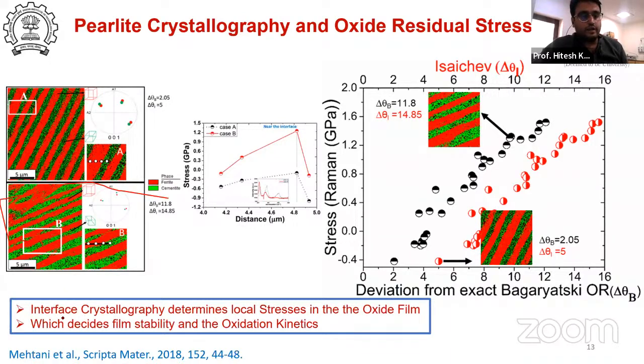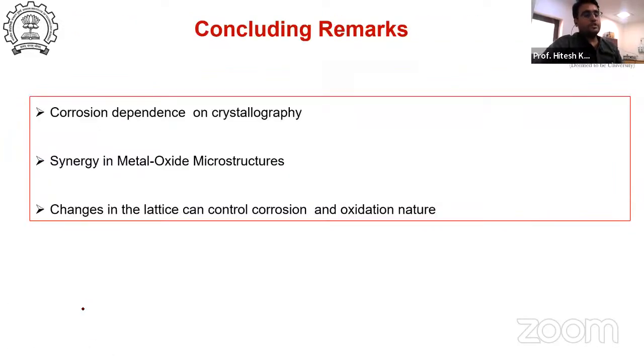In the end, I can say the stability of the oxide film and the oxidation kinetics change with the help of interface crystallography. So corrosion resistance depends on the crystallographic orientation, and there is a direct relationship between the metal oxide microstructure, which affects the oxidation kinetics and corrosion kinetics of the material, and a change in lattice is going to affect the oxidation and corrosion resistance of the material. These two papers we published recently in Philosophical Magazine and Scripta Materialia.